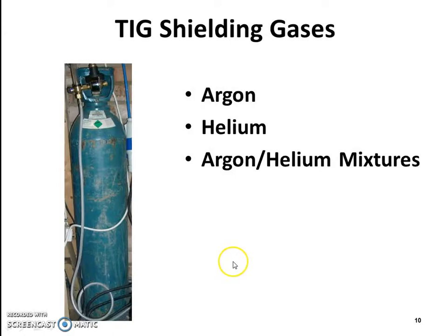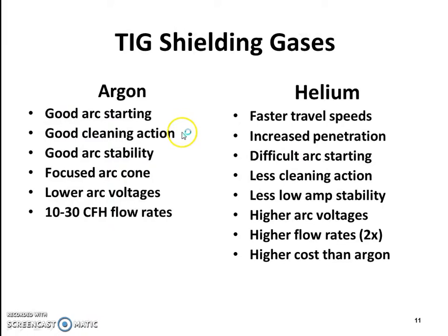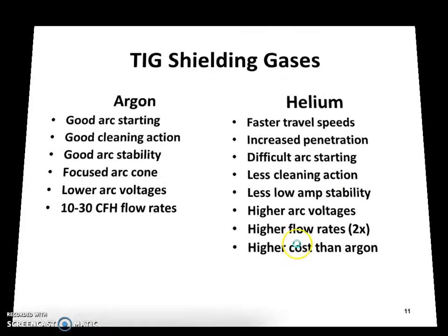The most used TIG shielding gases are argon-helium mixtures. The differences between the advantages of argon and helium. Argon: good arc starting, good cleaning action, good arc stability, focused arc, lower arc voltages, 10 to 30 CFH flow rates. Helium advantages: faster travel speeds, increased penetration. Helium disadvantages: difficult arc starting, less cleaning action, less low ampere stability, higher arc voltages, higher flow rates, higher cost than argon.